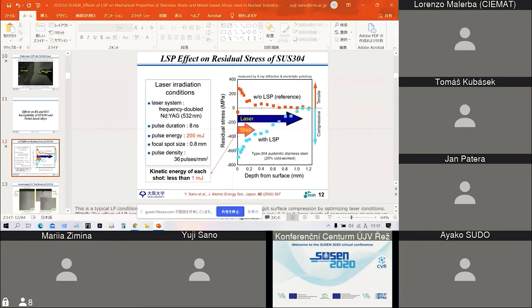We irradiate the laser pulse under such conditions onto the material, in this case SUS304. The result is like this. The horizontal axis shows the depth from the surface, and the vertical axis is the residual stress. Before irradiating the laser pulse, we ground the surface to make a tensile residual stress like this, and then irradiated the laser pulse to make a compression like this. You can see that LSP can induce compression to a depth of 1 millimeter or more. If you compare this result to that of shot peening, you can see the laser peening can induce a much deeper compression.